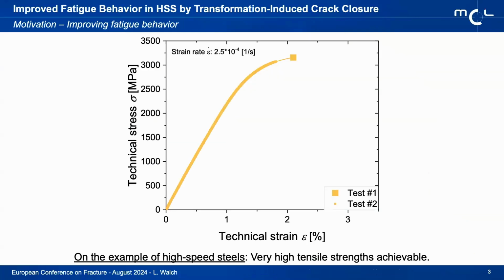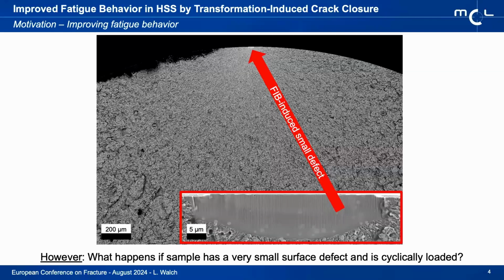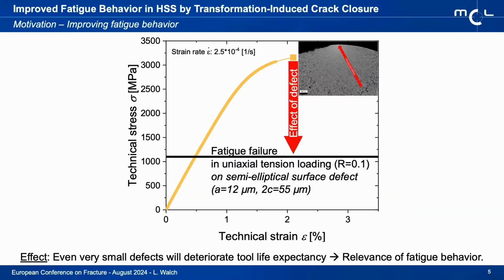Basically, they have extremely high strength, as you can see here, and even have some ductility left, and what's usually referred to as reasonable toughness. Of course, once fatigue is involved, that game changes, as is pretty illustrative here. For this specimen, we introduced a very small artificial defect of microstructural size, and after cyclic loading in tension, just after a few thousand load cycles, failure occurred at loads that are far below what we'd expect from the ultimate tensile strength. Of course, with fatigue, that's what we'd expect.